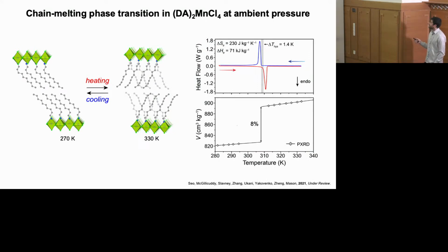And this 2D perovskite undergoes an order-disorder phase transition slightly above but very close to ambient temperature that's associated with quite a large change in volume, so about an 8% overall expansion in volume as the distance between these inorganic sheets increases as you go through this phase transition. And so we were excited about this because of both the large entropy change associated with the phase transition and the very small hysteresis as well.